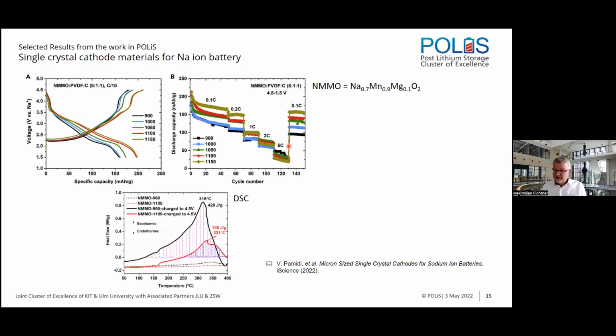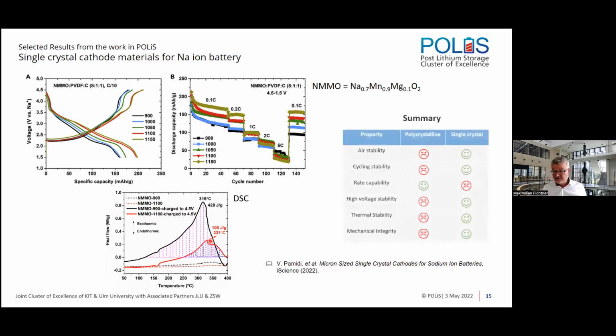Yeah, and this is probably the reason why these materials at high rates fall behind the polycrystalline ones. Another positive aspect is that if you heat these materials to elevated temperatures, more than 300 degrees, you see here in these DSC traces a strong exothermic event of the polycrystalline system, which obviously releases heat when it relaxes to a single crystal state. And this is much lower in the case of the single crystal system. So this is more stable and also more safe in that respect.